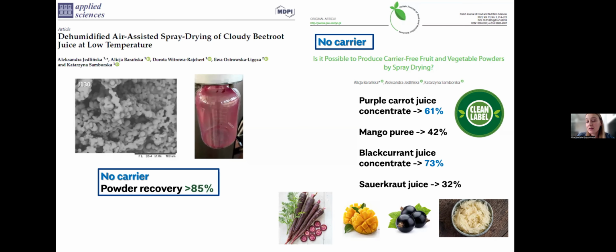We continued the studies, and we studied the purple carrot juice concentrate, mango puree, blackcurrant juice concentrate, and sauerkraut juice as well. And we managed to produce powders. In some cases, the powder recovery was not that satisfactory, but that was due to, especially for mango puree and sauerkraut juice, low content of solids in the feed material, and as well in the case of sauerkraut juice, due to a very significant content of the organic acid. But as you can see with the concentrate, it was possible to produce powders with very satisfactory powder recovery without any carriers.